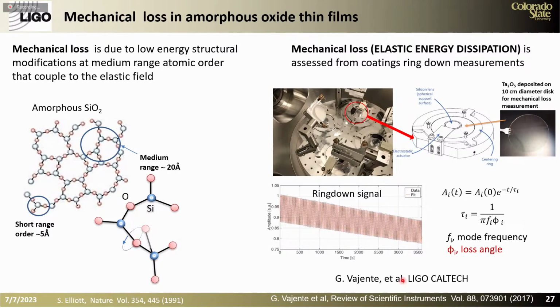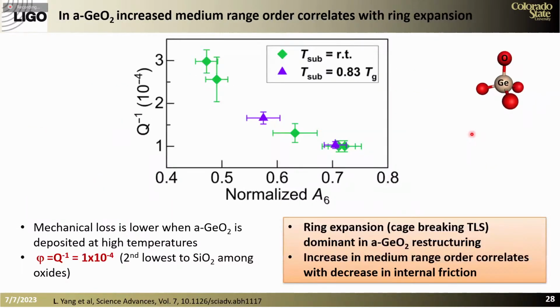coating thermal noise. So we have shown, as part of the study that we have done, that depending on the materials and depending on the doping that we use, we can control or affect the mechanical loss. And mechanical loss we can measure using a ring down cavity, as I show here. And then we can relate mechanical loss to coating thermal noise.